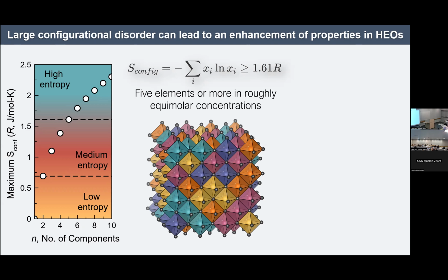And that is not an arbitrary number. That number actually happens at the limit where we cross over 5 components in the material. Whenever we have 5 elements in equal proportion, equiatomic, we say that the material crosses over from a medium entropy to a high entropy threshold.